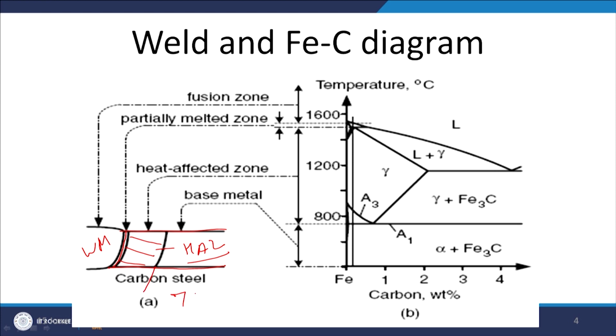Any zone which is heated above 723 degrees centigrade up to the melting point falls in the heat affected zone, and all the regions below 723 degrees centigrade in the case of carbon steels, which are not heated above this lower critical temperature line, will be in the base metal zone, because it will not experience major change in properties.